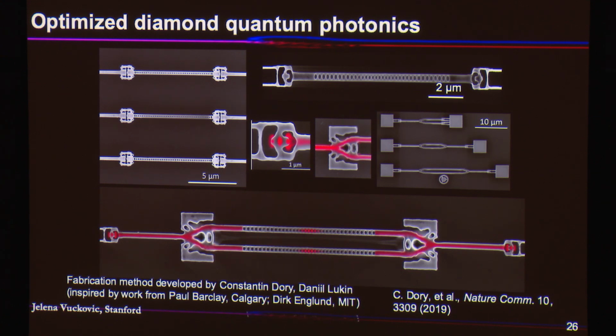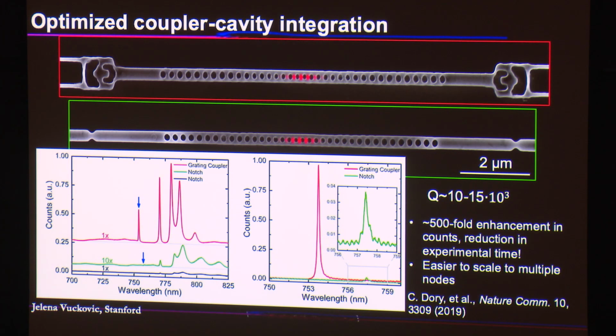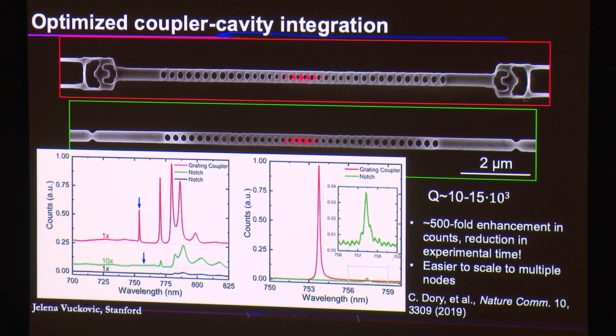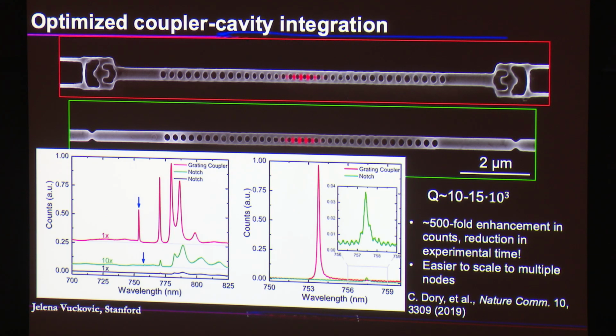And these are actual devices made in diamond, right? They don't look like intuitive photonic structures, but they do a lot of interesting things. So here is one example. I told you that this coupler has 1% efficiency. So we couple 1 out of every 100 photons, and then you wait for a while, and then you can integrate your photons and do statistics measurements. That's fine for one node, but would not be fine for more nodes. We wanted to show that we could do better than that, so we redesigned and optimized the coupler, and it doesn't look very different from your couplers, Andrei, but it does have higher efficiency. It actually has 27% efficiency in the same footprint.